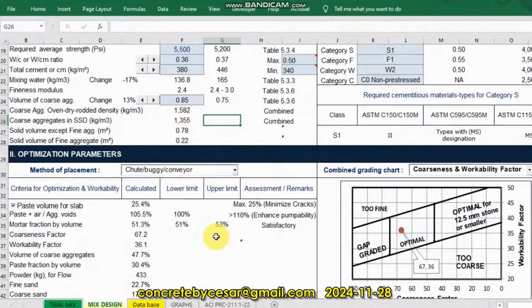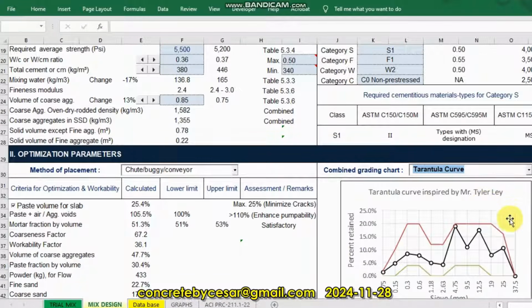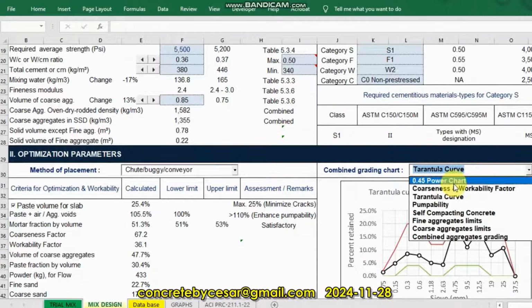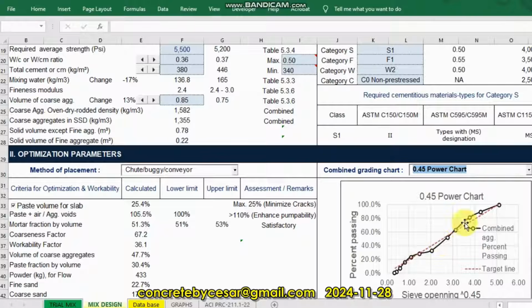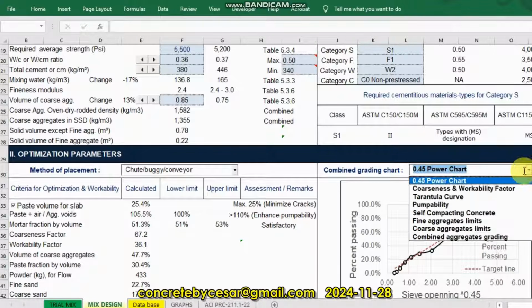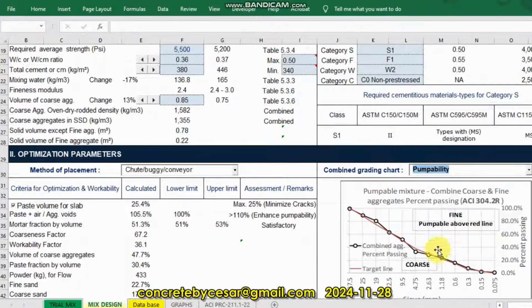So it's very easy to decide how to optimize your mix design that will be suitable for whatever application you need, for whatever grading chart that you propose to use. So let's try another chart. Let's say Tarantula curve. It's within the limit. If you use 0.45 power chart, it's almost very near to this target line, which is good. If we choose, for example, pumpability, it's almost near to this red line. So we have to be on the upper line to be much more pumpable.